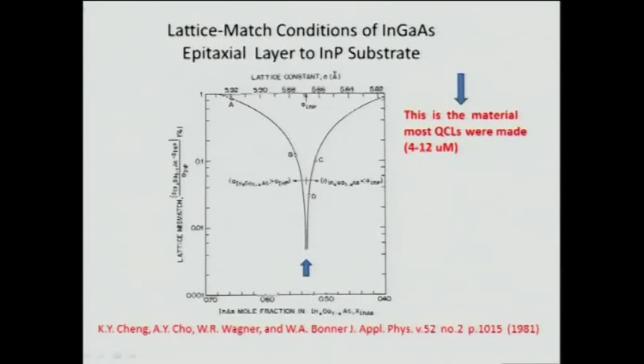And we were very lucky to have Norman K.Y. Cheng, a visiting scientist in my lab, to study the lattice match condition for growth of indium gallium arsenide epitaxial layers on indium phosphide substrate. Indium phosphide substrate has a lattice constant of about 5.87. There you can see the plot here, the lattice mismatch in percentage as a function of indium arsenide mole fraction in the indium gallium arsenide material. We had to have precisely 53% indium and 47% gallium in the MBE system to be perfectly matched to grow the indium gallium arsenide on indium phosphide substrate.